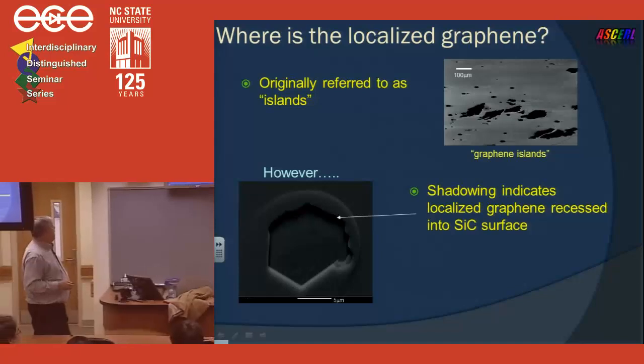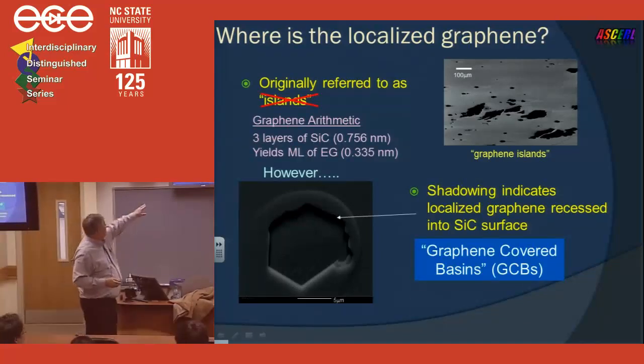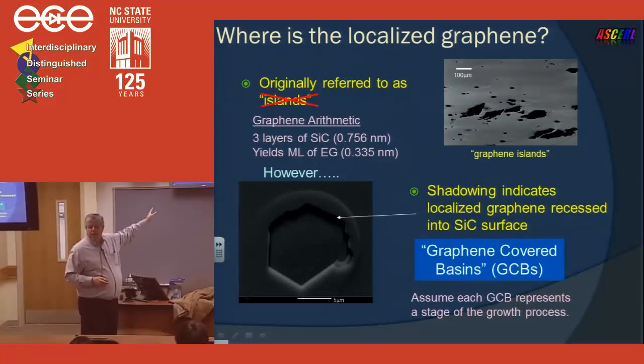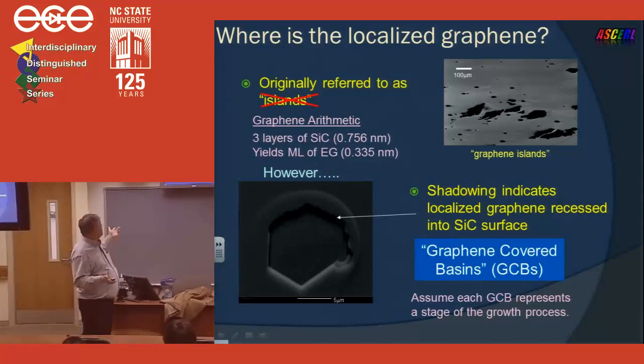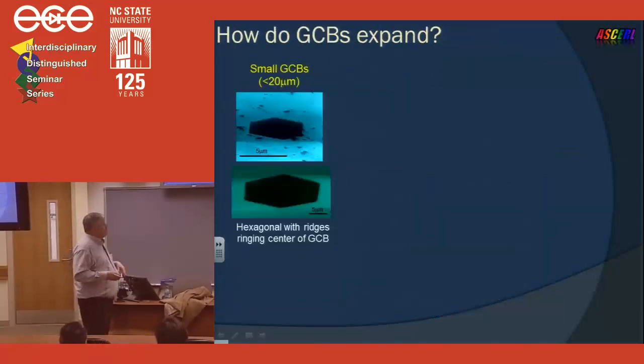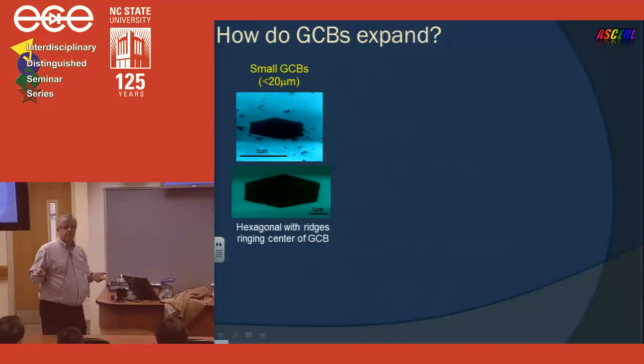There we go. And so instead of calling these little areas islands, we call them graphene-covered basins because they're below the surface. And remember, it's the graphene arithmetic: I have to take 3 layers of silicon carbide to make 1 monolayer of graphene. So it's always going to be below the surface by some fraction of a nanometer. Now, first let's take a look at some of these graphene-covered basins.